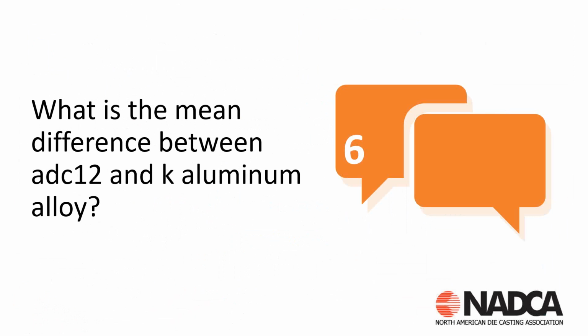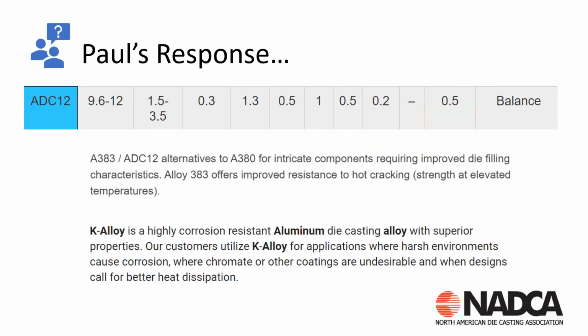What is the main difference between ADC12 and K alloy? Each alloy has very specific properties, and those come down to the chemistry. ADC12 is very close to a 383 alloy, and typically ADC12 is compared to 380. When comparing ADC12 to an A380 alloy, it has better fluidity and better resistance to hot cracking at elevated temperatures. That alloy has a slightly higher silicon level and a slightly controlled copper level, but when comparing directly to 380 alloy, it can improve the fluidity and make a more fluid tight casting or a leak-free casting.